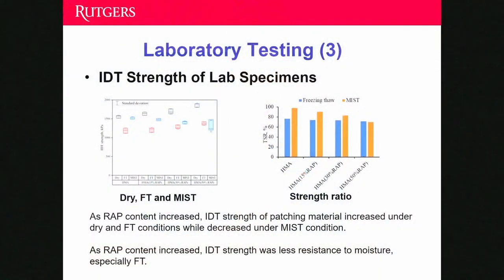And this slide shows the IDT strength of the lab specimen. We can see that as the RAP content increased, the IDT strength of patching material increased under dry and freezing thaw conditioning. This is understandable because the RAP material was coated with very aged binder, and the RAP was stiffer than the new HMA. However, under the moisture conditioning, we found the IDT strength decreased with the RAP, probably because of the negative impact of the hydraulic scouring effect.